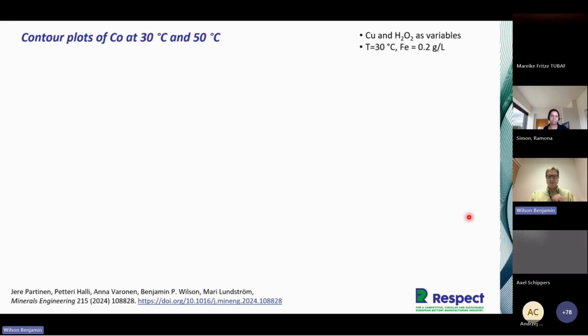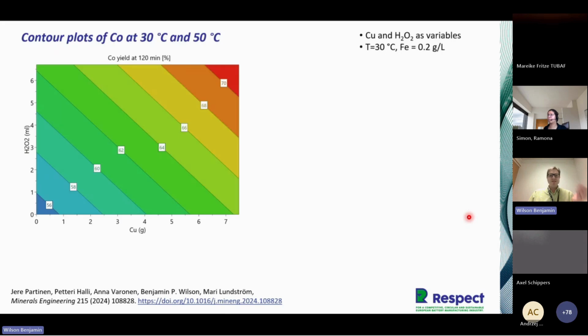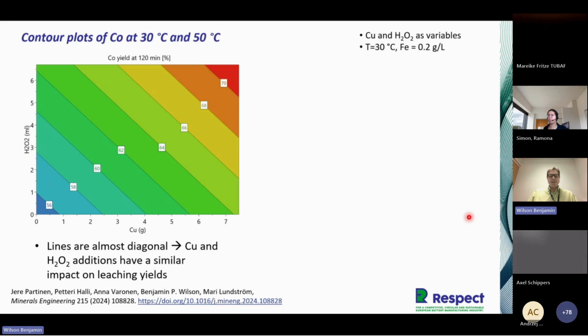But what kind of results could we get out? Well, we can do some contour plots. This is for cobalt, where we have copper and peroxide as the variables. In this case, the temperature was 30 degrees and the iron level was quite low at only 0.2 grams per litre. So as you can see here on the left, the lines are almost diagonal. We have peroxide on the left axis and copper amount along the right axis, and these are at about a 45-degree angle.